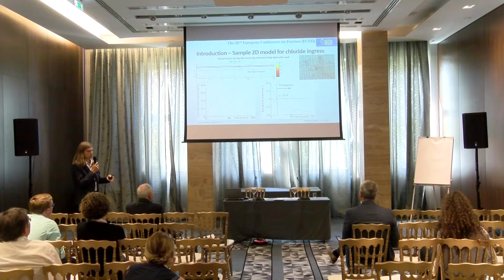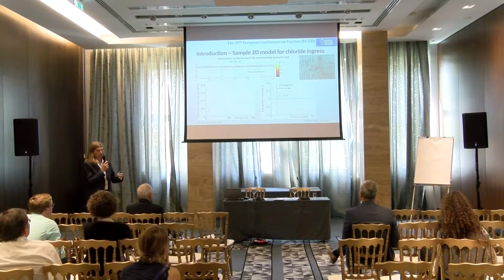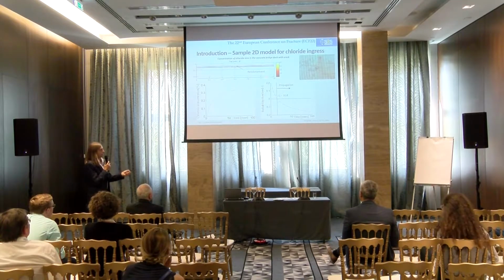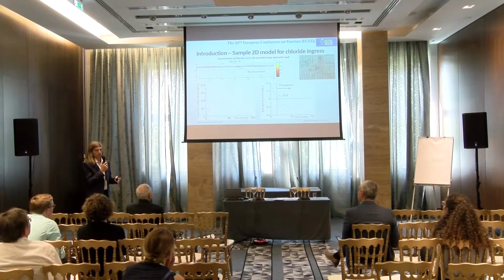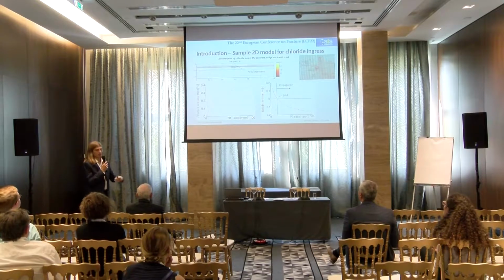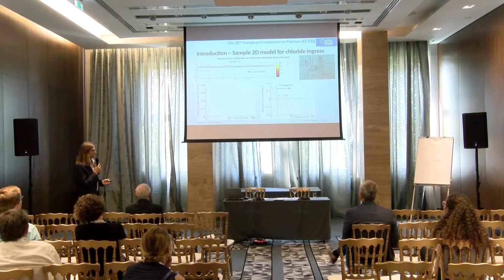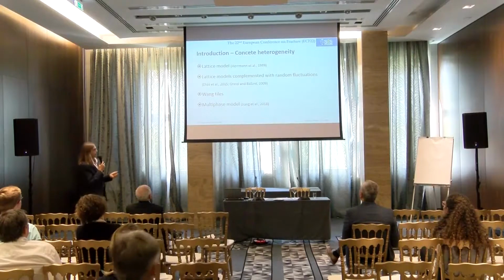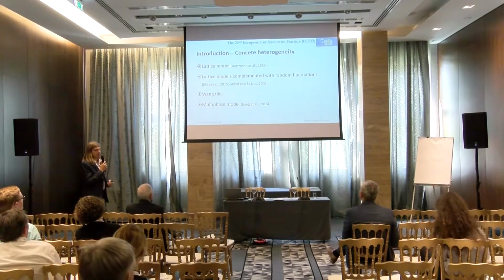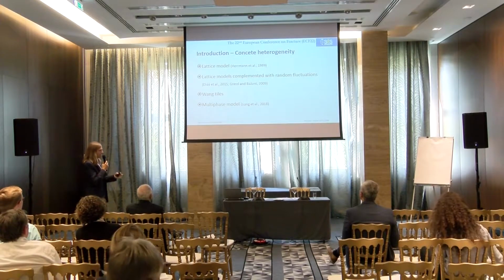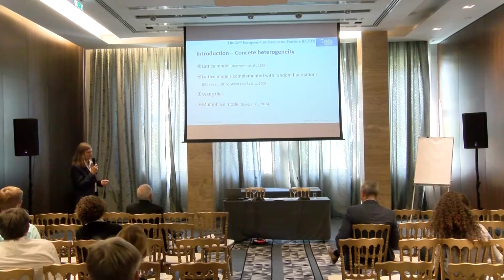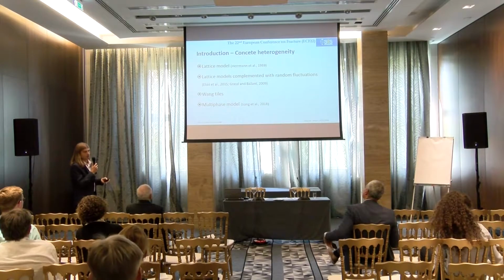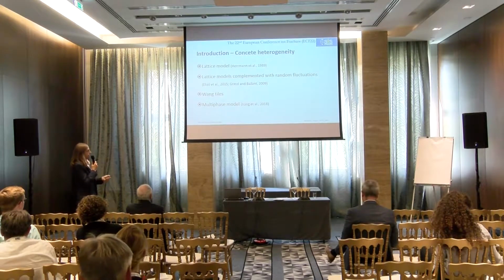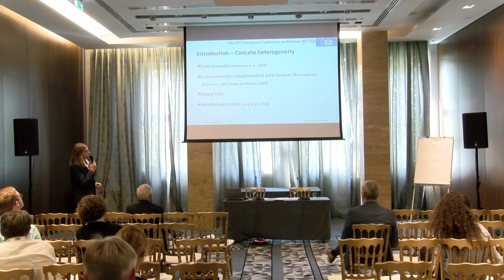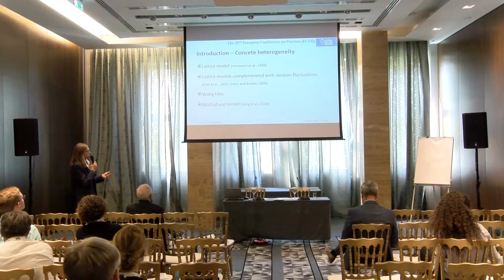So this is the illustrative picture of the model that we have, and currently it can be probabilistic, but the material property, diffusion coefficient of chloride, was considered to be homogeneous over the area, and the probability was added via Monte Carlo in repeated simulation steps. And we tried to evaluate the possibility of introducing the heterogeneity, and we are here at the conference for fatigue, and for example, in case of a fracture process in concrete, the lattice models for the structural mechanics process modeling were introduced, and they were even complemented with the probabilistic approaches and random fluctuations, or other approaches for the heterogeneity multiphase model.